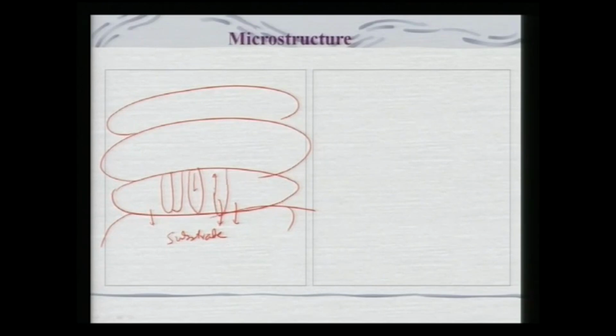So we see the overall growth is also occurring in that particular direction where heat is being extracted. We can see formation of certain columns like this, and similarly the other layers also start forming a columnar structure which is more like that. So generally we have a lamellar structure, these are nothing but lamellae, and then we have a columnar grain structure which basically forms in the thermally sprayed processes.